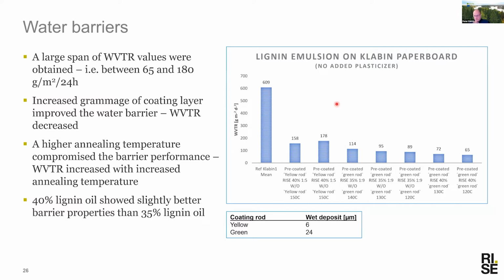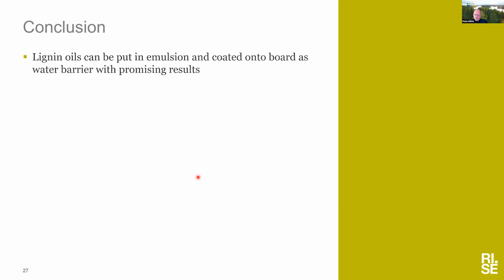No, it's modified actually. It's not just plain kraft lignin that we mixed. But generally, what we can see is that we get something that is a promising water barrier. It's not a perfect one, but it's at least below 100 grams per square meter a day. So if we can draw some sort of conclusion, it is that we can put the lignin oils in an emulsion, and we can coat board with it as a water barrier with promising results.